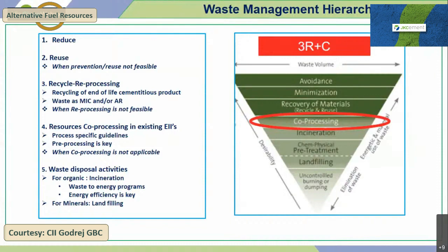For co-processing, which industry is suitable? Thinking that way, the cement industry is much more suitable, because in the cement industry we produce clinker at a temperature of around 1450 degrees Celsius. As per the study, in the range of 800 to 900 degrees Celsius, all the AFR minor elements, along with other elements, get merged with the clinker. So cement co-processing is the best way to utilize this AFR.